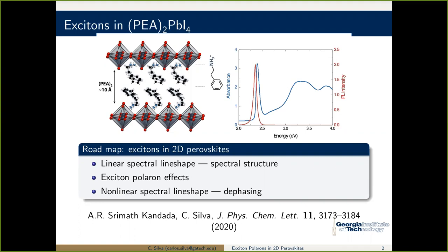But what I also want to communicate is that these are very, very dynamic lattices. So Pat, who I believe is in the audience, has had some recent work on perovskites, arguing the solvation-like properties of the counter ions and so on. The idea is that this very dynamic system, it's a very soft lattice, it's an ionic lattice with degrees of motion of the organic cation that really influence both the disorder as well as, through very strong electron-phonon coupling, all the properties of the system.